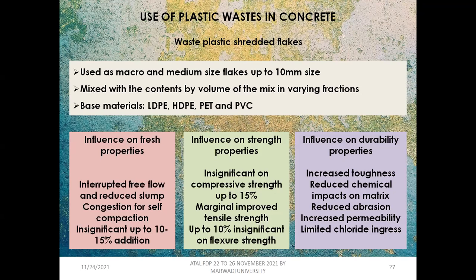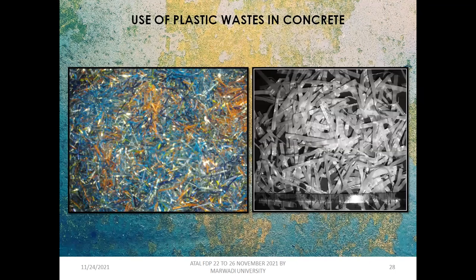Influence on the strength properties: insignificant on the compressive strength up to 15%, marginal improvement in the tensile strength, and 10% insignificant improvement in the flexural strength. But as far as the durability is concerned, increased toughness, reduced chemical impacts. And again, the similar behavior that we have noticed in granules, flakes or fibers again contributed in the same way. So these are images of the fibers that we have used in the concrete.